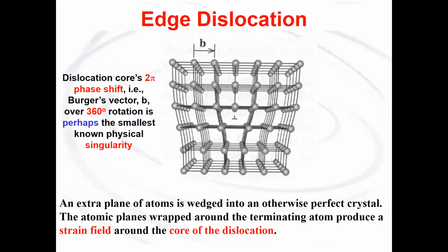This is an image that many of you have seen of an edge dislocation, where we can have an extra plane of atoms in an otherwise perfect crystal. The extra plane terminates in the crystal, and the atomic planes we can see bending around the core of the dislocation. One of the interesting features of the dislocation is that if we do a Burgers circuit around the dislocation, we get a 2 pi phase shift over a 360-degree rotation. And whenever we have this situation at the center, there's a physical singularity, and the singularity at the core of the dislocation may be the smallest known physical singularity.